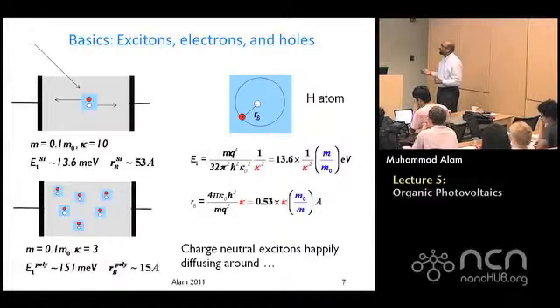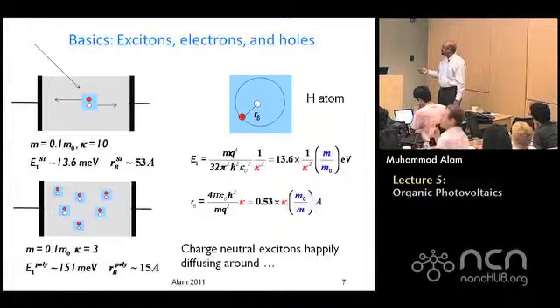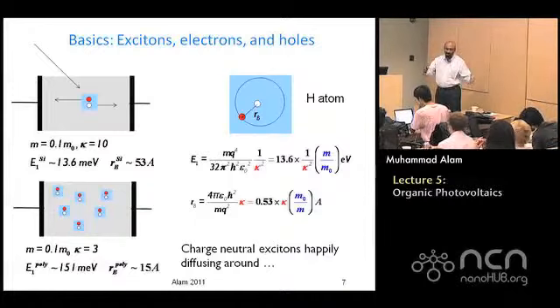Not true for organic materials, because organic polymers have low dielectric constant, on the order of 3 or 4, so this factor is not as big. And therefore, normal temperature cannot kick them out, right? Also, this radius is such that unless you use a heterojunction, you cannot even pull them apart, because they are just close together and moving together all this time. And if you apply a p-n junction field, they don't care, because the p-n junction field is a factor of 100 smaller than what you need. That's the problem. Is that clear?